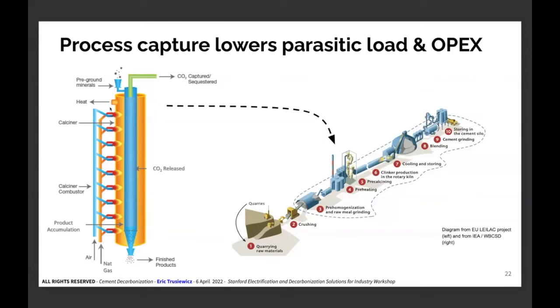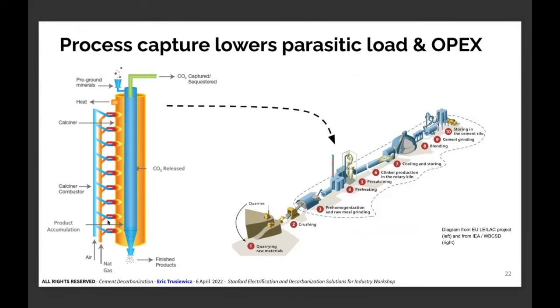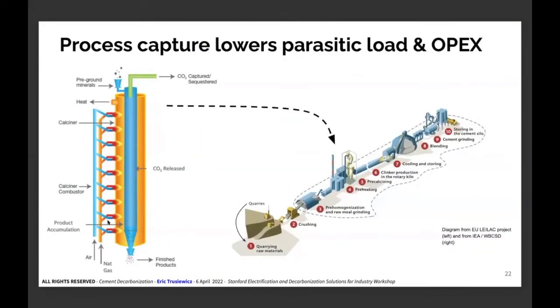And again, electrification is really interesting here. This is a gas-fired version, but Calix has also developed a fully electrified version of this, both for magnesium and for calcium, and it's used in the cement process. So that's an interesting innovation, I think, on the calcination section of the cement plant. And calcination is interesting because it happens around 900 and not 1500, so it's a lot less challenging for electrification. So that's about the carbon capture.